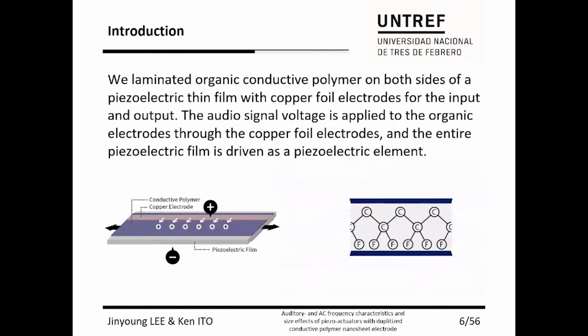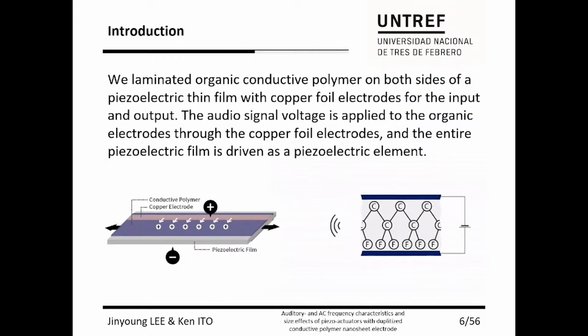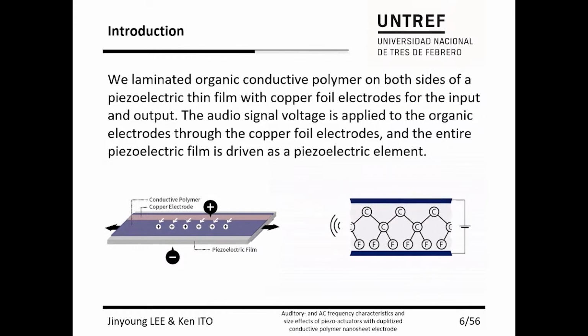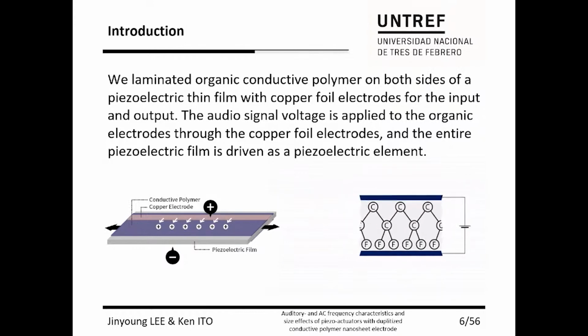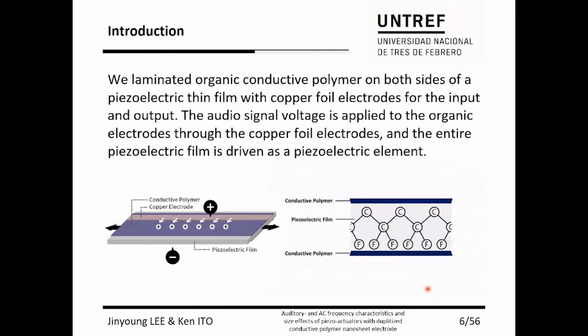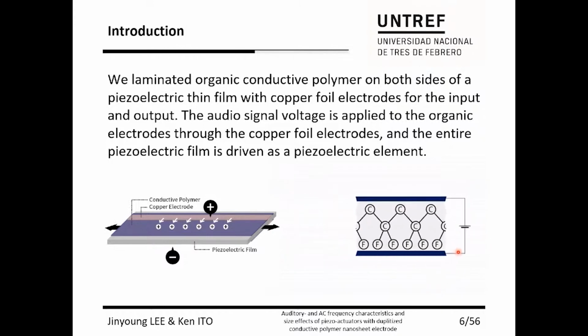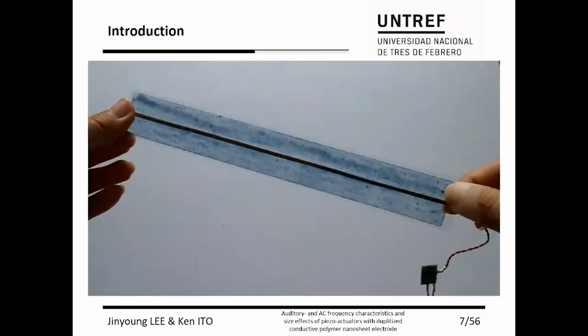We fabricated a capacitor-type actuator with piezoelectric film and conductive polymer. We laminated conductive polymer on both sides of the film. When the audio signal, that is AC volts, is applied, the entire film vibrates by expanding and contracting. This is the actuator. Because of its ribbon-like feature, we call it a piezo ribbon actuator.